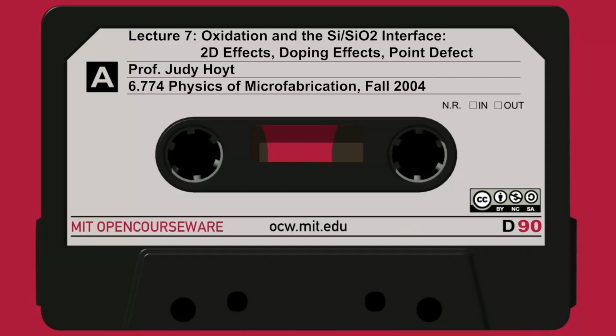And it's this generation rate G that's directly proportional to the oxidation rate. So if I oxidize faster at a given temperature by upping the partial pressure, I will generate a larger rate of injection of interstitials, and I'll get more boron diffusion in the buried layer.